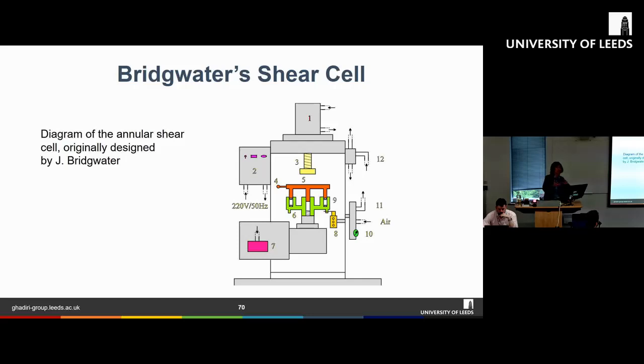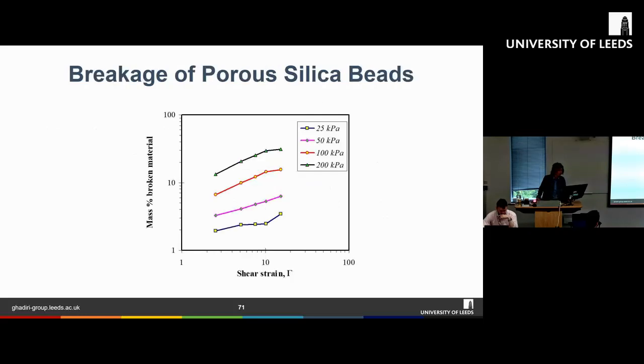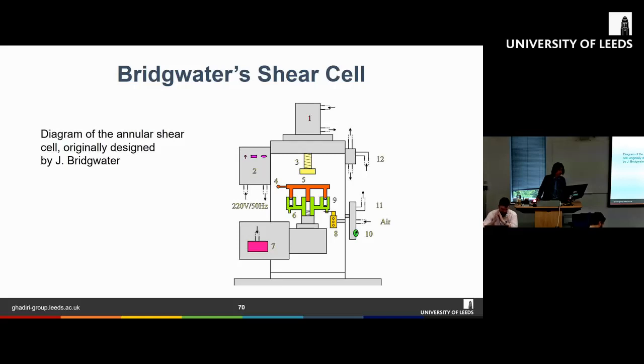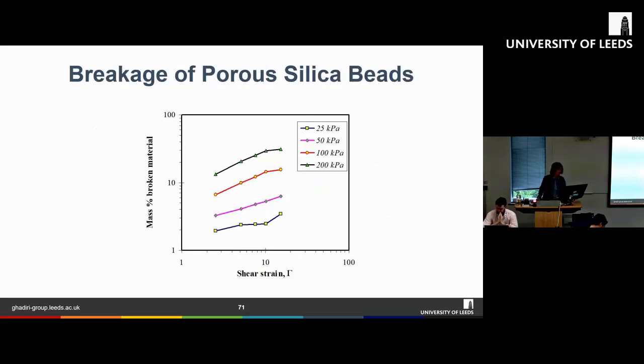And then if you're looking at how particles break as a result of shearing, here we have the shear cell of Bridgewater. Essentially how it works is that you put some powder in this annular shear cell, you apply a normal load, you shear it, and then the particles break as a result of the shear deformation. And here is an example showing the mass of broken particles as a function of shear strain under different normal loads.